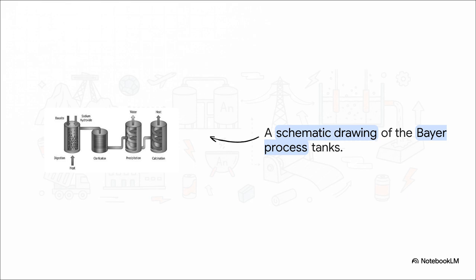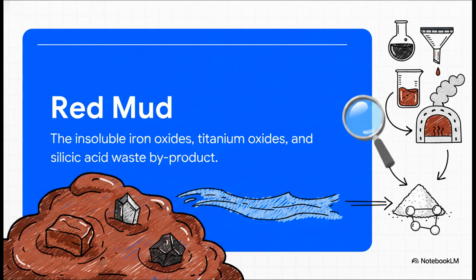It then moves through clarification and precipitation tanks, separating that valuable alumina from all the waste. Now, you can't dissolve all that rock without creating a ton of leftover junk. While the aluminum dissolves, the insoluble iron oxides, titanium oxides, and silicic acids settle out, forming this massive waste byproduct that industry insiders call red mud.